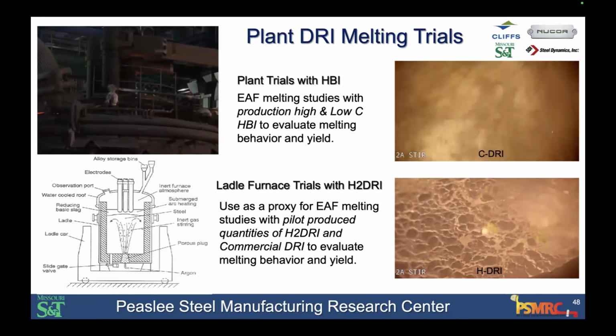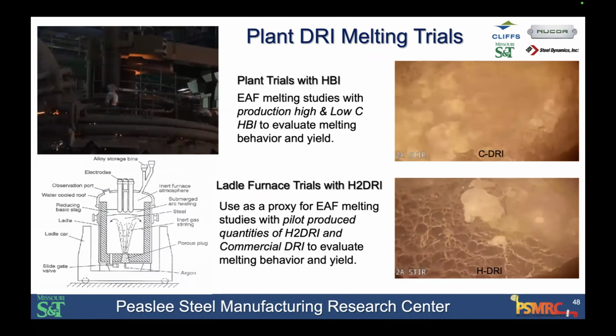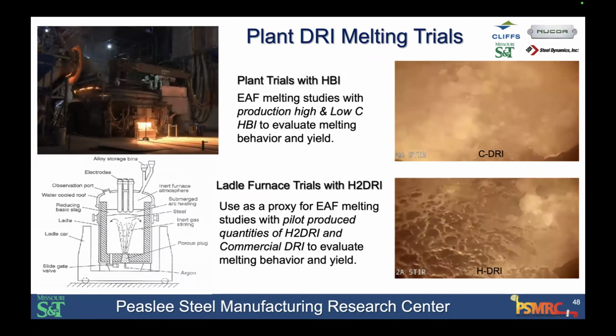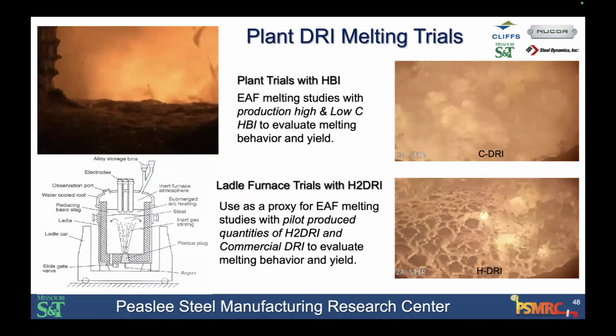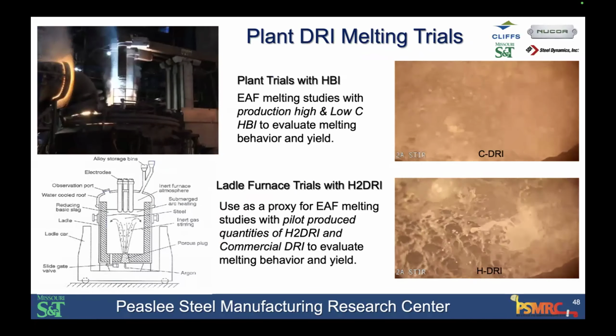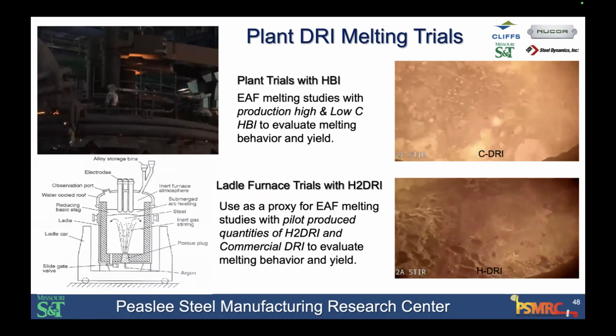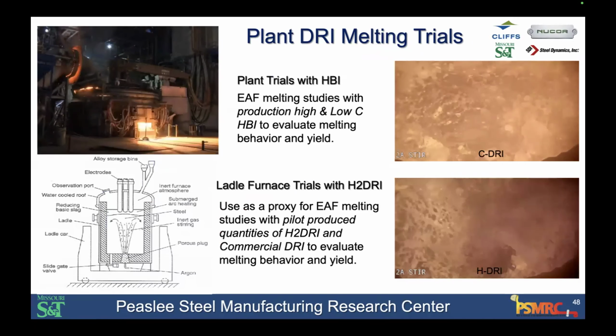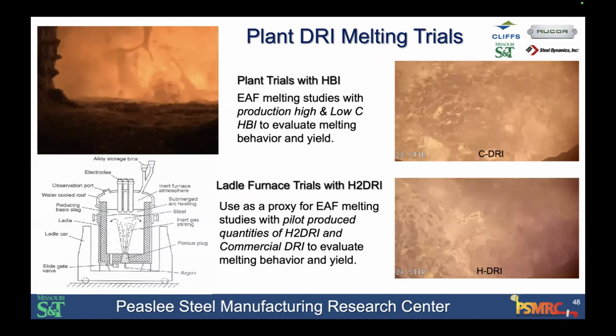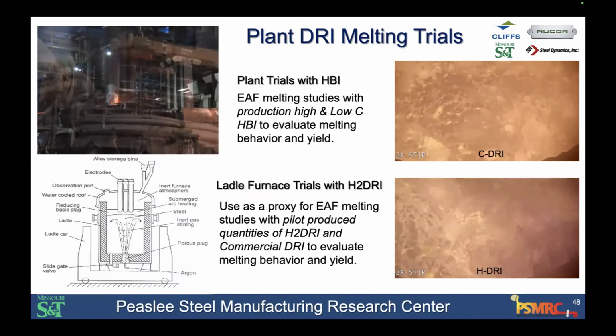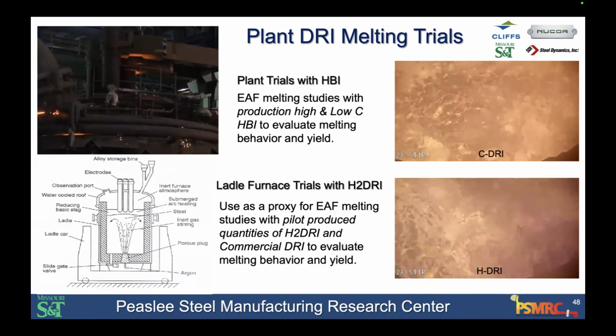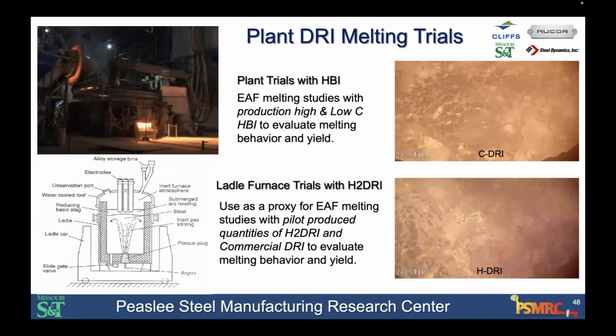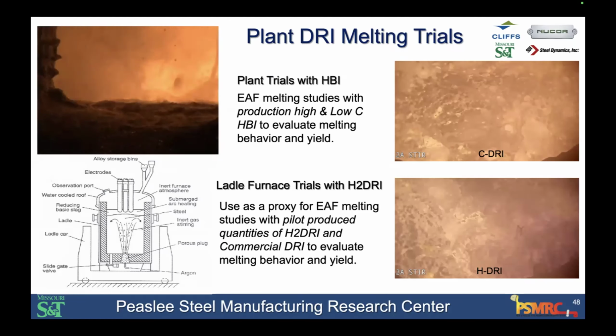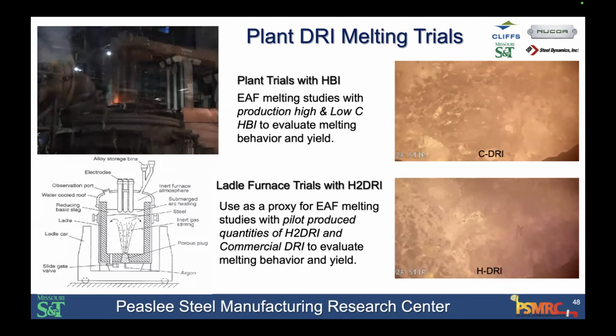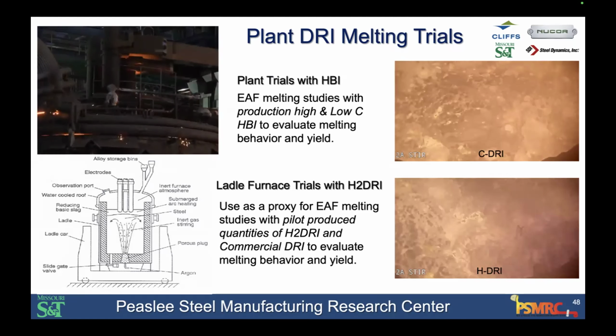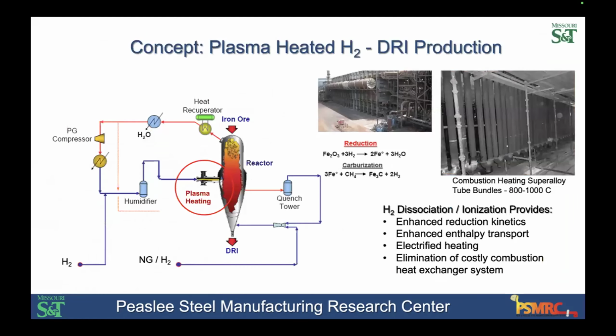I mentioned that we also did plant trials, and this actually shows a comparison of carbon and hydrogen DRI being fed into the slag metal system, in this case, an LMF that was set up to act as a proxy for the EAF environment. And this allowed us to feed material and film the material very easily while studying what's going on in the steelmaking slag world, and examine the effects of bridging and the activity of the gases.